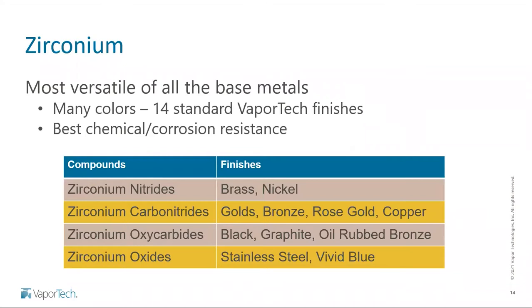Okay, so let's talk about each of these individually. So let's talk about zirconium first. Like I said, this is the one that we use most often, by far more than any other. 14 of the standard VaporTech finishes are based on this. I think we have on the order of 20 or 22 standard ones. So 2/3 of them are based on zirconium. And this material, not only can you make a lot of colors, it also has the best chemical and corrosion resistance. It's just a really durable metal. It's very stable in a wide range of environments and against various chemicals.